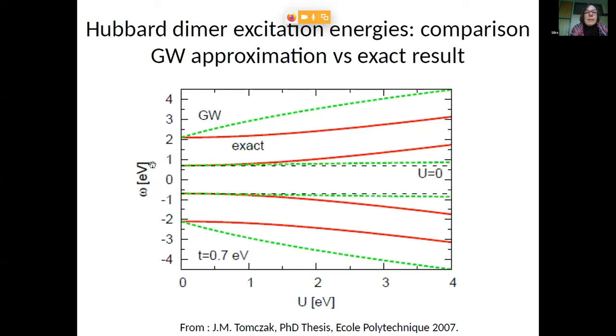So apart from these details, the overall bonding, antibonding description is there, and now it's a quantitative question if it's enough to open up the gap in VO2, and that is indeed, I would say, what has been observed in the different works, namely that things depend quite strongly on how exactly you do the GW calculation. Do you do it self-consistently, based on which orbitals and so on? What is your starting point? So I think the overall answer, does it open up the gap? It can, with the caveats that you can deduce from this plot here.